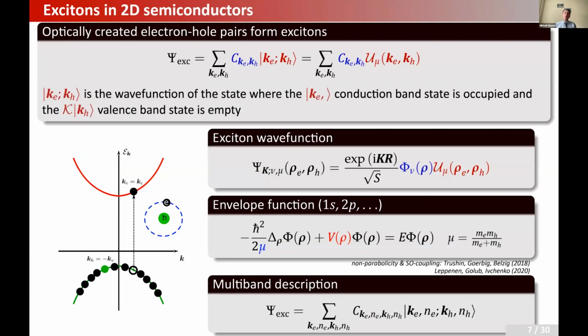Let me say a few words about how the excitons are formed, and I will start with a very simple situation. You have a two-band model, the valence band and the conduction band, and we promote an electron from the valence band to the conduction band. In this simplest possible two-band approximation, we can present the wave function of the exciton as a product of the two-particle Bloch function, or two-particle Bloch amplitude, a periodic function with the period of the lattice, and some coefficients.